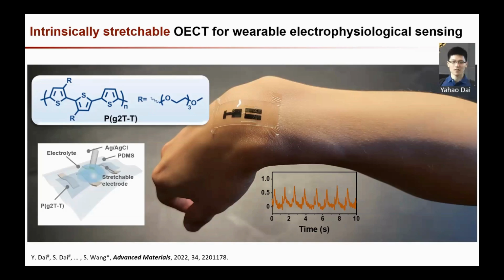It's a stretchable property. So for this, we honestly didn't do too much in designing new material. It's a pretty conventional design for this redox active semiconducting polymer. The only distinction that we identified based on the hypothesis of the mechanical property for the design is to choose a unique backbone architecture to have a so-called asymmetric arrangement of the side chain unit to weaken the pi-pi stacking between the backbones, because the pi-pi stacking will have some non-overlapped orientation. So then this helps this polymer to be able to very effectively dissipate the stretching you are applying in the way that the sliding between the different polymer chains can happen.